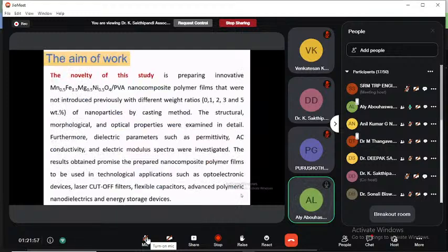Now I will talk about the sample preparation, how we prepared this sample. At first, the spinel ferrite was prepared based on a flash auto combustion technique. We used ferric nitrate, manganese nitrate, magnesium nitrate, and citric acid. By using the flash auto combustion method, the ash powder was then ground to a fine powder and annealed at a temperature of 700.